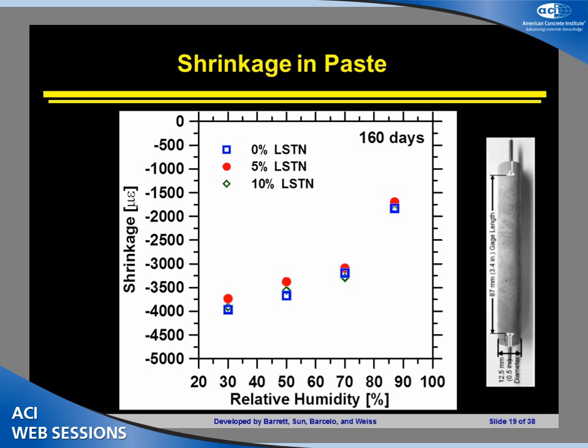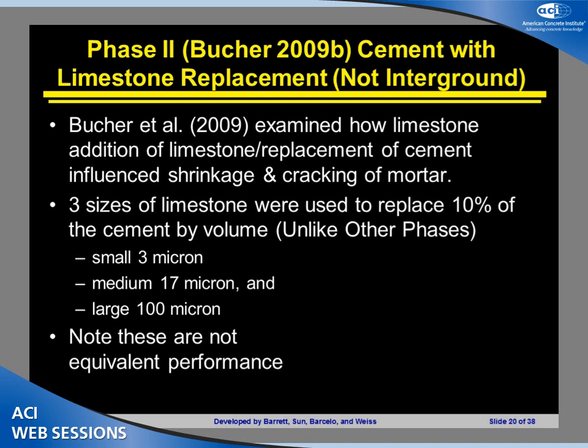And what you can see again, 0%, 5%, 10% limestone, the results all lie up on top of each other within the statistical variability that you would expect in this system. So again, the main point that I want to drive home is even though we have different Blaine fineness numbers, about 80 points finer for the 10% limestone system, we see identical shrinkage over a really wide range of relative humidities that we'd be looking at here.